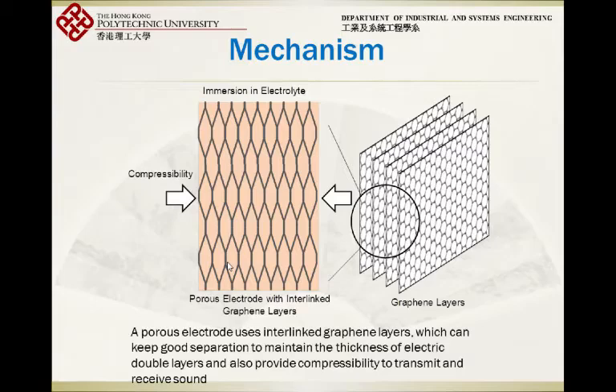The good thing about this mechanism is that this device was originally designed for energy storage, so it can store a lot of energy. It also has a high power density, so it can transmit power very quickly. We don't need a high DC bias or high DC voltage to drive it. We only need something from 1 to 6 volts, which can be considered a very small voltage for ultrasonic transducers. Of course, we probably cannot go higher, because at higher voltage the electrolyte will be decomposed. We know electrolysis, right? It will decompose into something else like gases. So we try to use the compressibility of this porous graphene structure. When it compresses, it can generate sound.